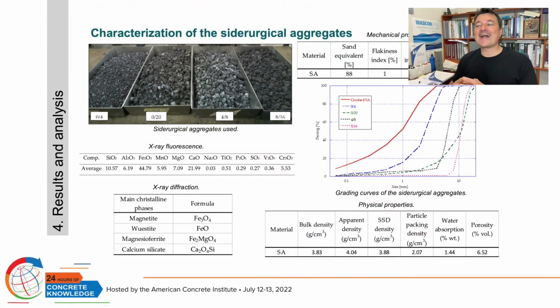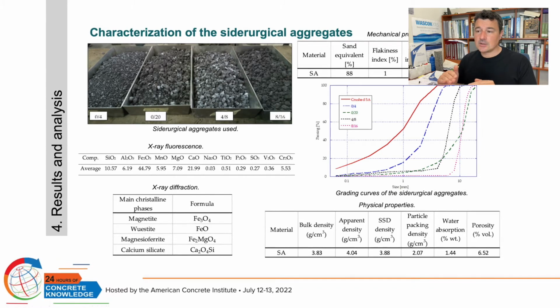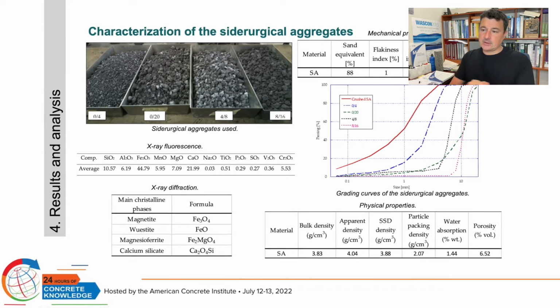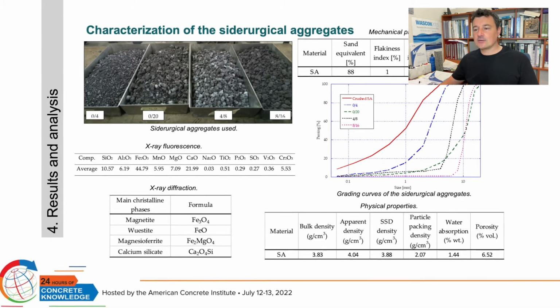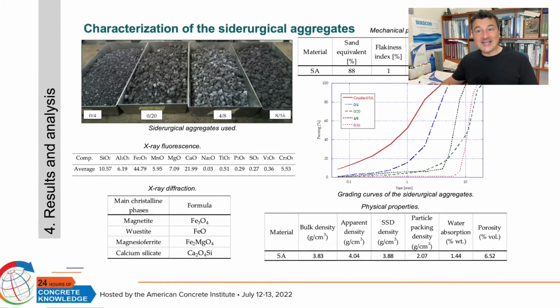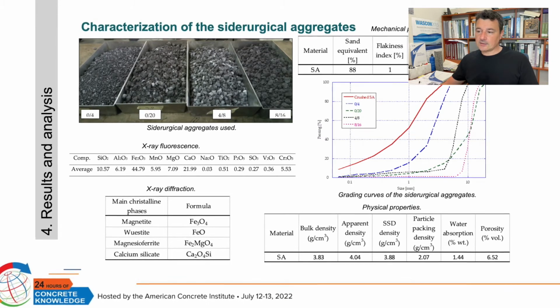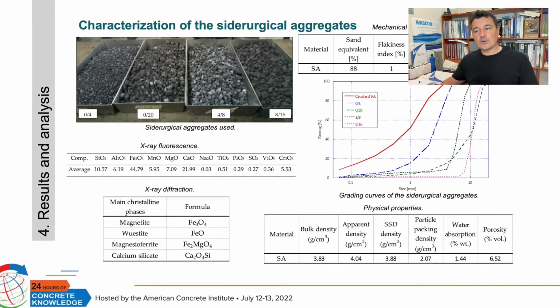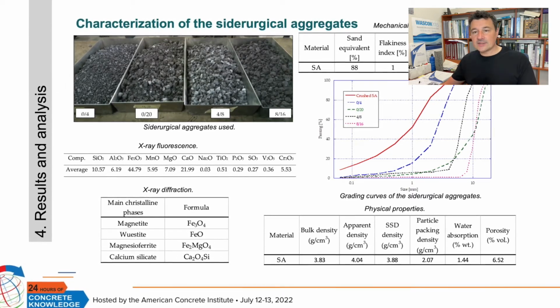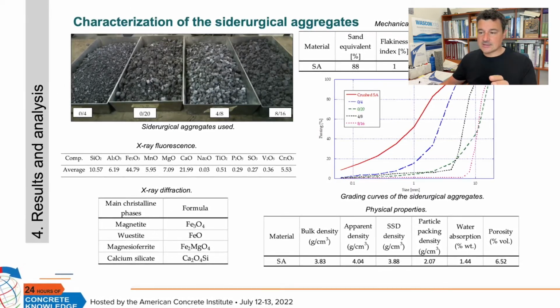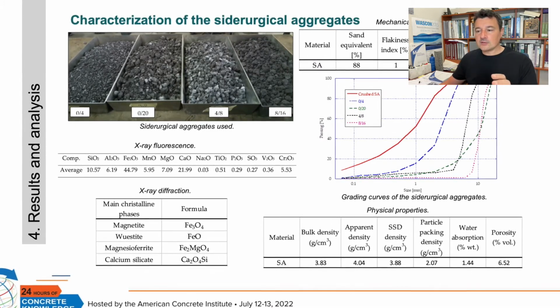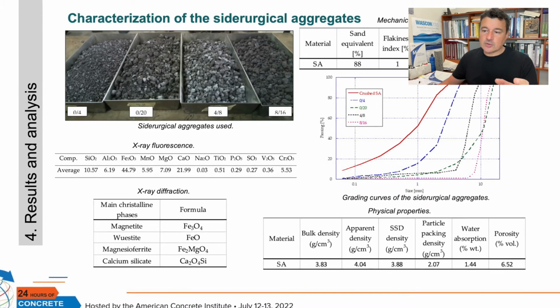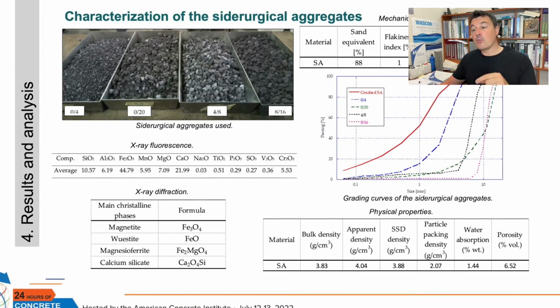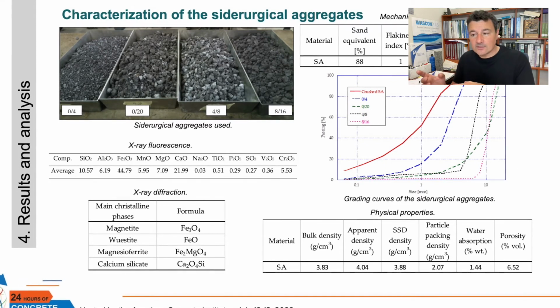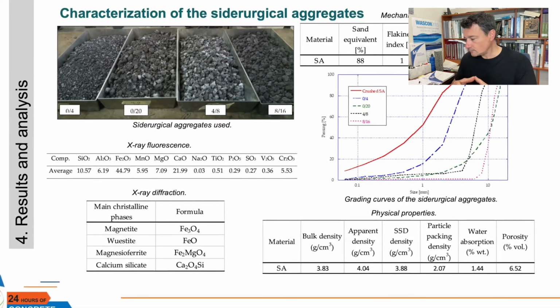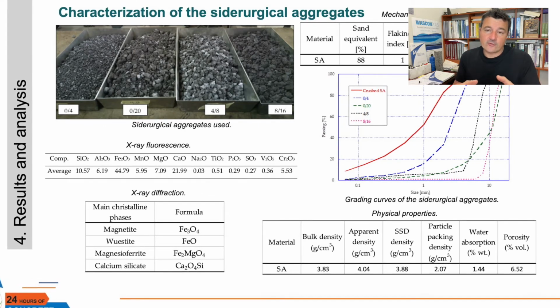Let's see now what the properties of the siderurgical aggregates are, with the results of this project. In this picture, you can see different sizes of the material, in millimeters: 0/4, 0/20, 4/8, 8/16. And in this table, the X-ray fluorescence of the material, so the chemical composition in oxides. What is the main component of the siderurgical aggregate? You can see here that iron is the most important component by weight of its composition. It is logical because it comes from steel production.